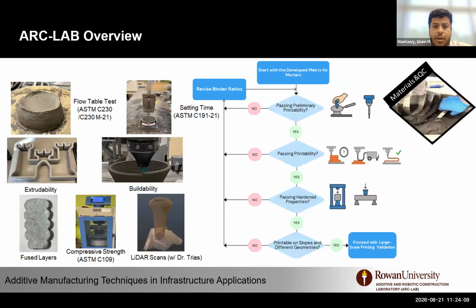So in general, for our lab, we created a workflow or flow chart to develop different concrete mixes from mortar to UHPC and others, where we do quick testing, the flow table test and setting time, to quickly assess the printability of the material. And after that, we do what we call performance-based printing. After we initially develop the material, we go through extensive testing through the printer with many different printing parameters, extrusion rate, printing speed, etc., to evaluate the printability of the mixes.